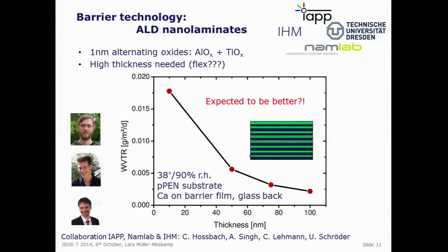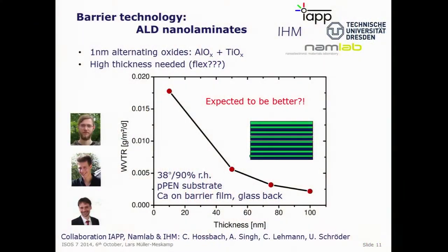This is interesting, but of course we wanted to go for real barriers now. So we went for ALD, and with our collaborators at NAMLab and IHM, we had a look at alternating oxides, aluminum oxide and titanium oxide nanolaminates, in this case 1 nanometer thick each, and then stacked. And we measured the barriers of these on a PEN substrate. And you can see, okay, with increasing thickness, WVTR gets much better. This is on a planarized PEN substrate. And this is the calcium on the back of the barrier film, so we measure a barrier. Okay, so this works pretty nicely.